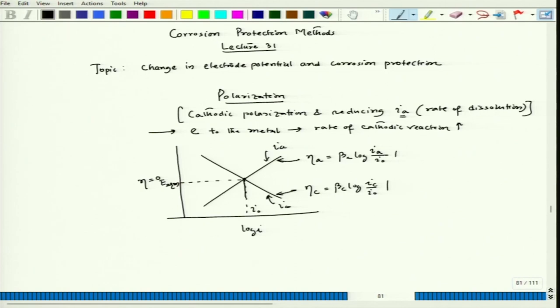So, as we have seen, if we can go down in the potential range, so this is E prime, and I could see that the IA, if this particular metal maintains the equilibrium and stays at this position, if we can send negative current or electron to the metal, definitely the potential will drop and the IA will reach here. So, that IA is less than I 0. Okay. So, at equilibrium, IA equal to IC equal to I 0. So, that means this IA, which is let us say prime, is less than the IA what it used to be had it maintained equilibrium, fine.